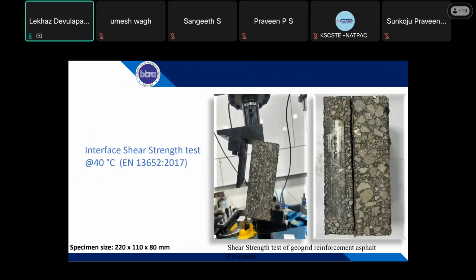So this is the interface shear strength test. This is one kind of test we have developed in our research to check, if you place a geogrid in between the asphalt layers, whether there is any delamination or bonding issues. We started this with different